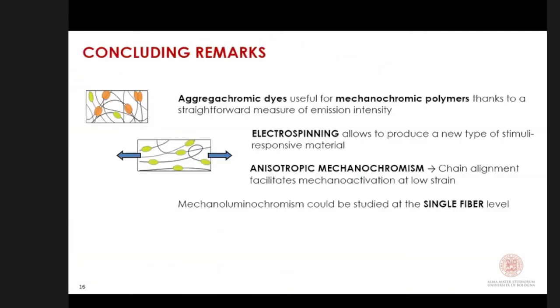So, to conclude, this telechelic aggregachromic dye could be used to make mechanochromic polymers, which can be processed with different techniques, for example electrospinning, and this technique allows us to study the anisotropic mechanochromism, with which we discovered that the alignment facilitates the mechanochromic activation at low strain values. Then we were able to study also the mechanochromism of the single fibers.